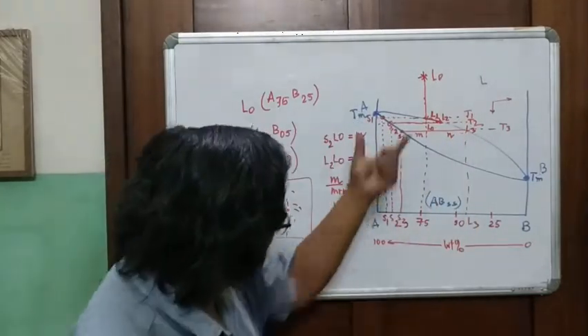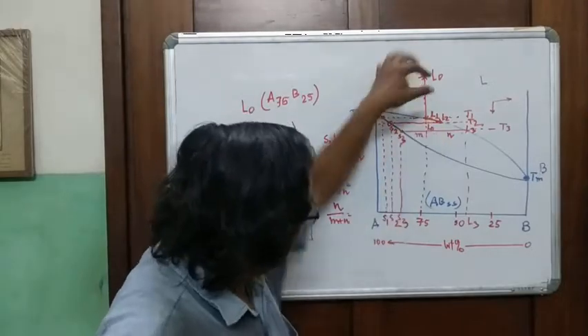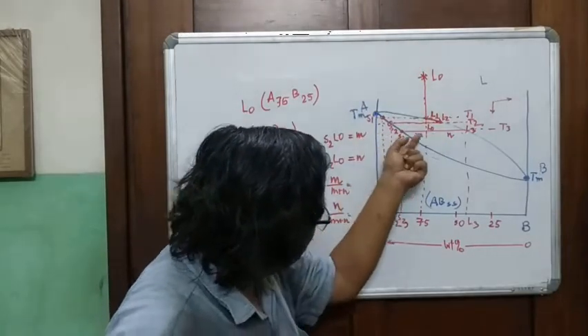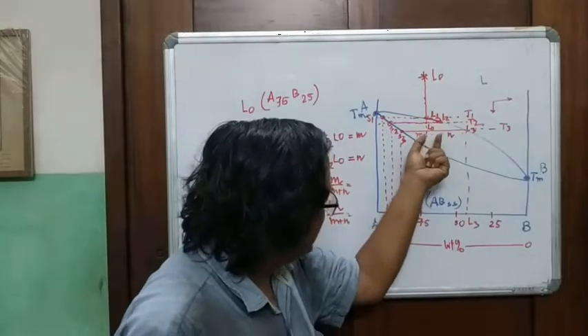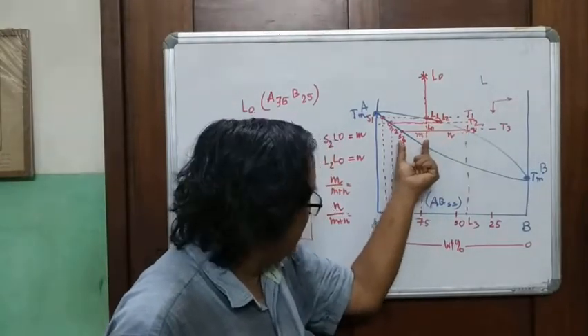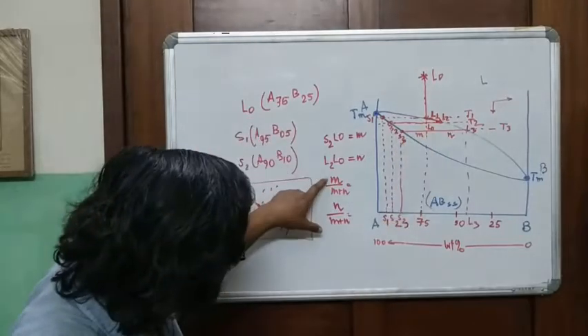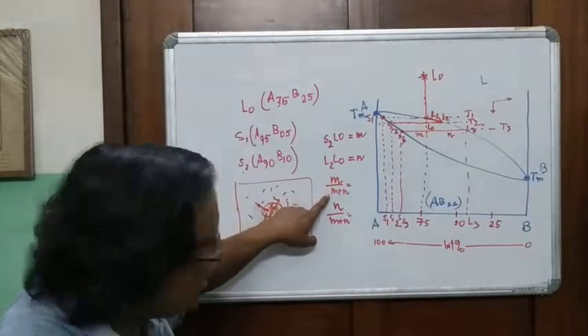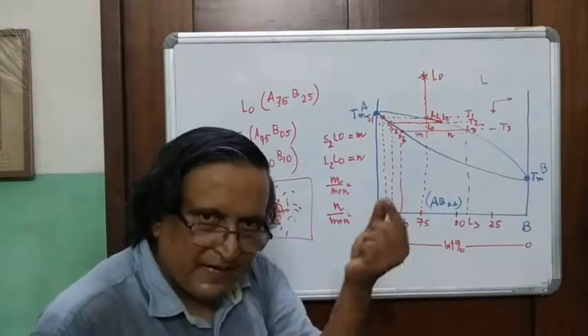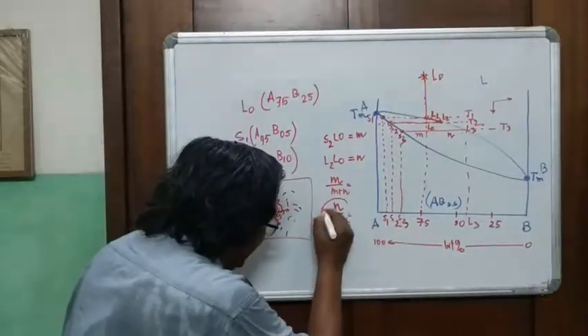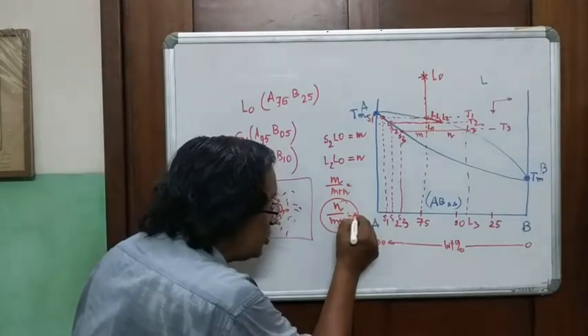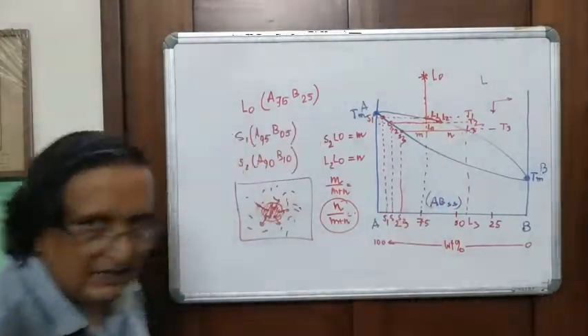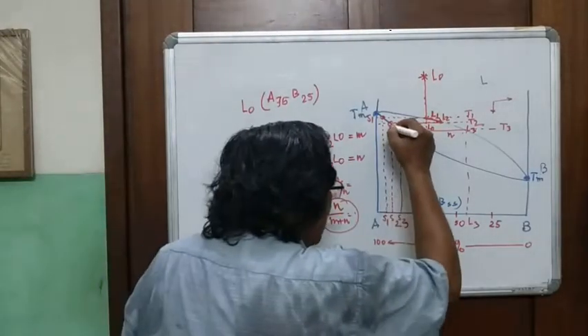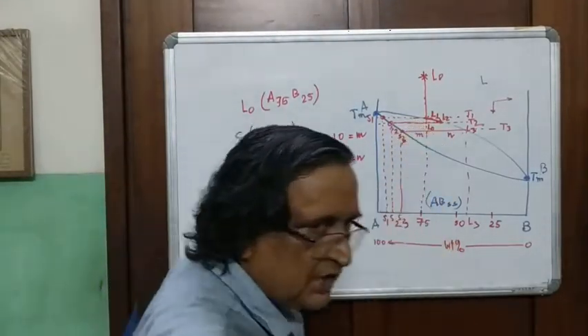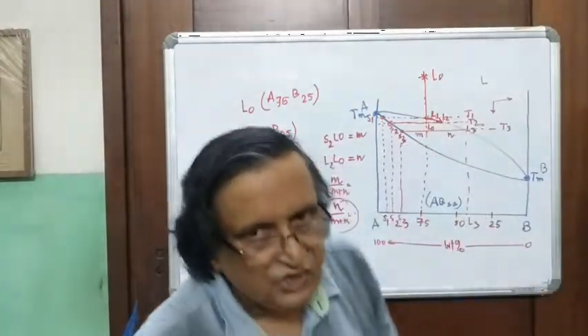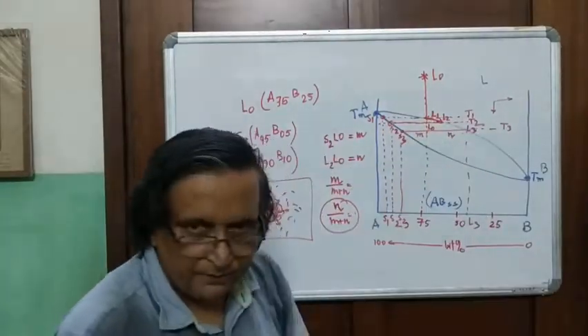You can see you started from M with N almost equal to 0 here, and now as crystallization has progressed, N has become larger and larger, and M has become smaller. And you can see M divided by M plus N, which is the fraction of the liquid, is becoming less, and N divided by M plus N, which is the fraction of the solid, has been increasing. And at the same time, the solid composition itself, the mineral composition itself, is changing, as is the composition of the liquid.